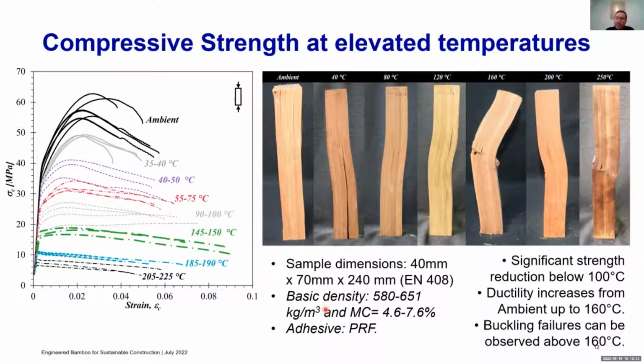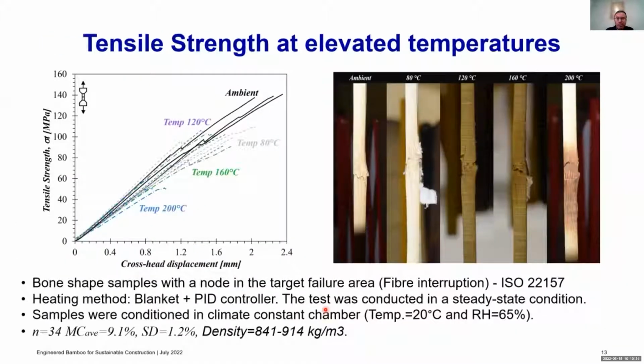We did a lot of tests on tension as well, trying to understand the effects of temperature on the tensile strength of the material. We used a heating blanket. We used, in this case, bamboo strips because it was easier to make the test. And because when we did compression, we also did round bamboo tests and laminated bamboo tests. So at the beginning of my research, I was working with both materials, with round and laminated bamboo.